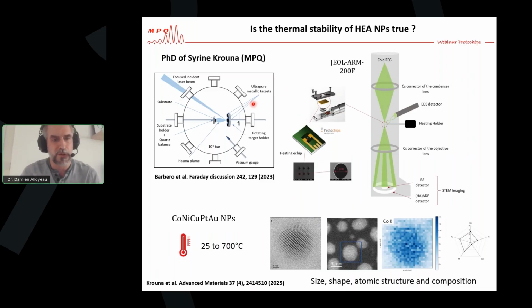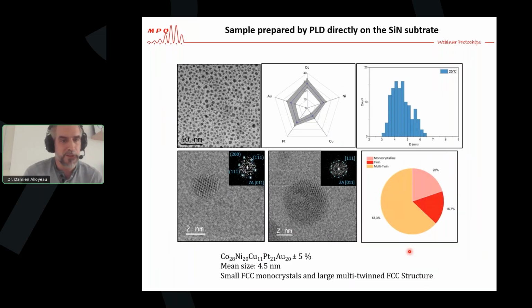So we fabricate those nanoparticles using PLD, the same synthesis method used to obtain the cobalt platinum nanoparticles. You use a laser to irradiate a metallic target, you create a plasma, and you condense this plasma on the surface. So we had the nanoparticles, and we used the Protochips gas cell system under vacuum to observe the thermal behavior of those nanoparticles between 25 and 700 degrees, using high resolution and EDX analysis in STEM mode. Here is the starting point of this experiment. The as-grown nanoparticles, you see you have particles of roughly 5 nanometers. You are close to the equiatomic compositions. Small nanoparticles are mostly monocrystalline, but the larger nanoparticles are usually polycrystalline. So that's the starting point.